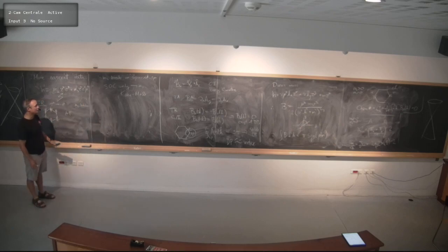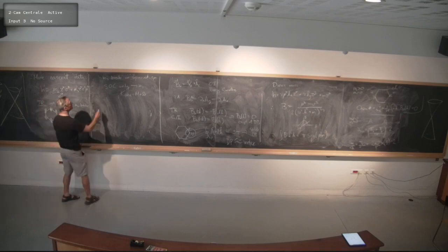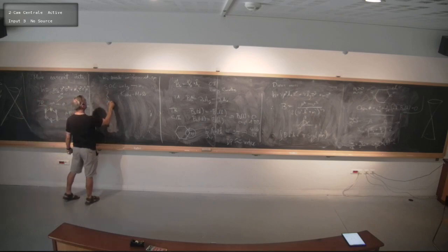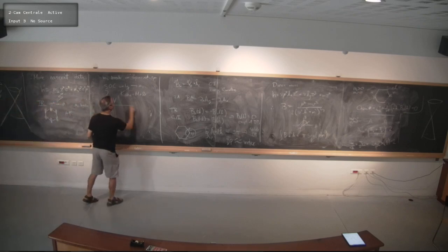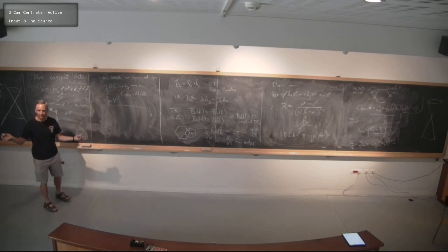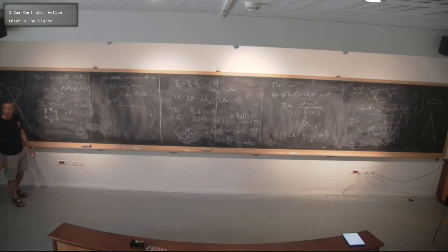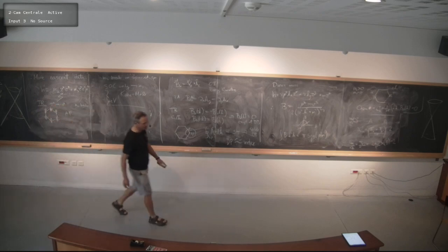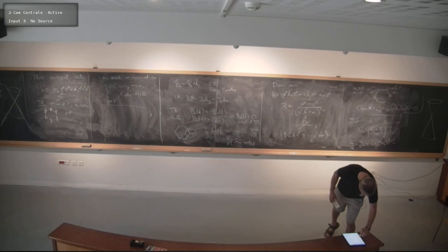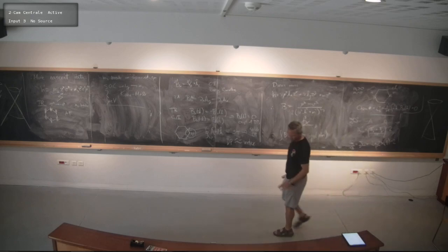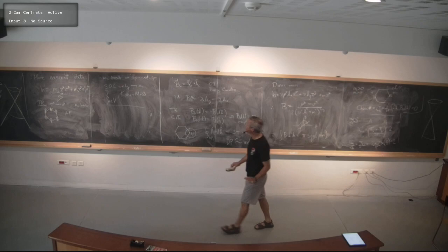It turns out now that spin orbit coupling is extremely weak, kind of. The appropriate number for this is in the microelectron volt energy scale, so this is really not observable in pure graphene. But we should keep in mind that maybe due to interactions, such a mass could be generated. Okay. So there's lots of potential for interesting states that could occur in graphene by these types of mechanisms. All right. So this is actually the end of the single layer graphene review, okay?